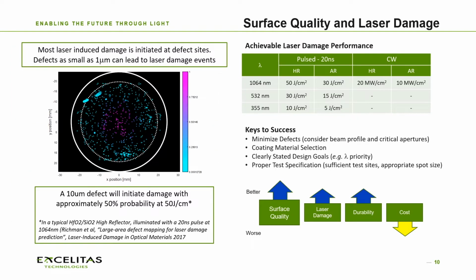So naturally, one of the key specifications when it comes to laser damage is surface quality. There is a direct relationship between the laser damage performance of an optic and the surface quality, and that goes beyond any particular laser system type. Most laser damage is initiated at defect sites, and defects that are really small, smaller than you might think, can lead to laser damage or be statistically meaningful in the evaluation of laser damage probabilities.